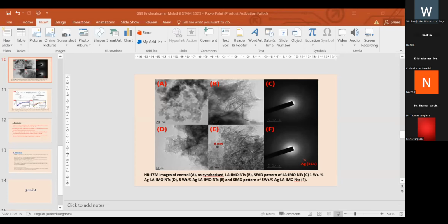According to the SAD pattern, it's semi-crystalline, an in-between stage of amorphous and crystalline nature. So according to this, we can say that it's in-between, and we can observe some silver plane also. Is it clear? 111 plane? Yeah, the Ag 111 plane is observable here.